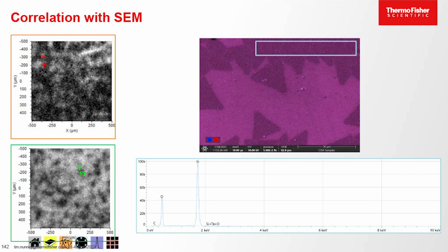So, harking all the way back to James's first thing this morning, we look straight through them. And so we just see the silicon and the oxygen from the silicon oxide wafer, and we don't see any trace of the molybdenum or the sulfur. We just look straight through it. So you do need both techniques to be able to do it.